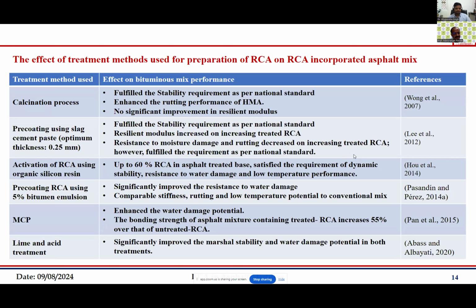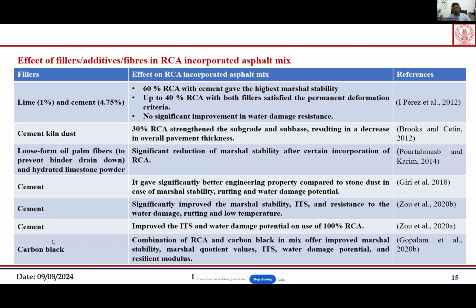Yes, please. So there are different treatment methods people have used, like the calcination process, pre-coating, and other methods to activate RCA. Then pre-coating the RCA with the bitumen emulsion, using lime, and many of the studies have used cement also, because cement is a very popularly used filler material in the asphalt mixture and it is easily available. So many of the studies have used cement to coat the aggregate and then use it in the asphalt mixtures. So that way they have found that it has performed really well.